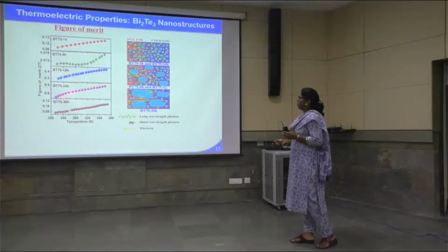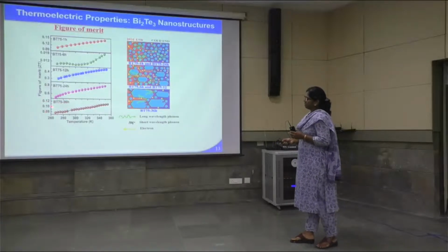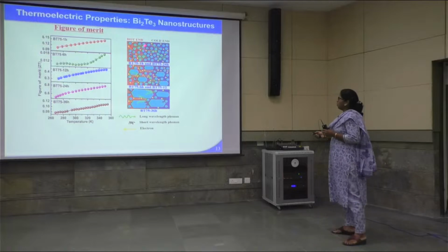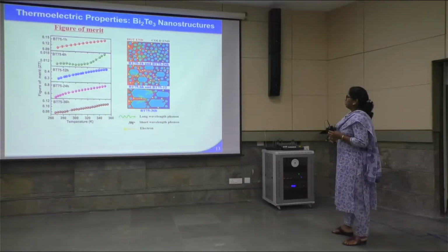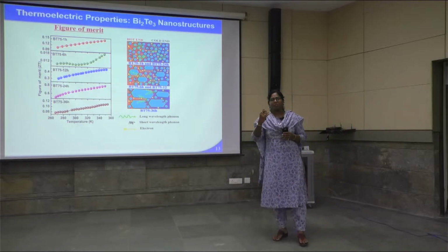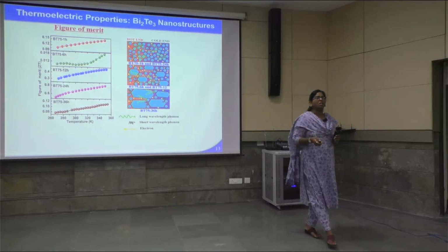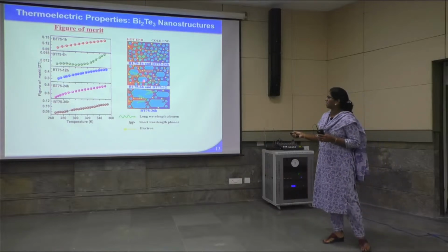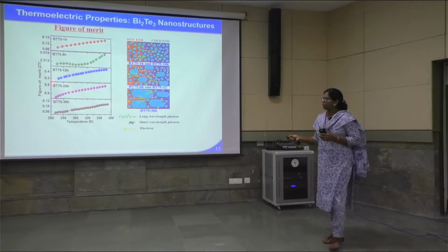This is the result of why the thermoelectric figure of merit values have become higher. Because what happened here is that the long wavelength phonons are very few, and that has helped. Out of the three parameters, the thermal conductivity played a major role here. Because of the lower thermal conductivity values in these two types of morphology,